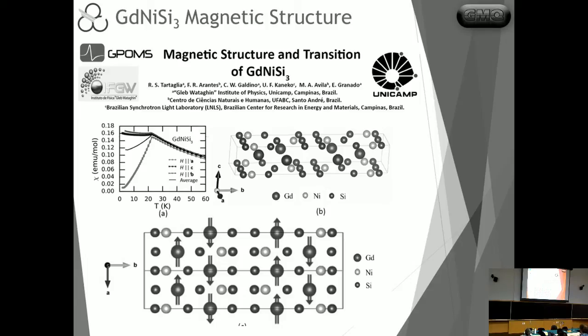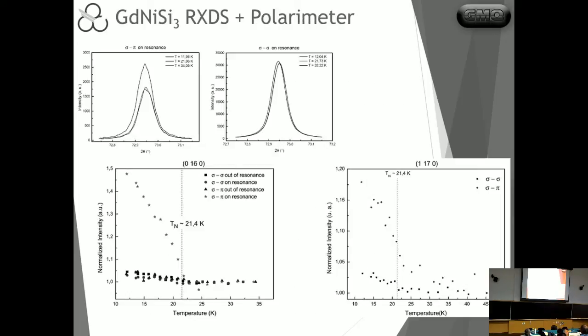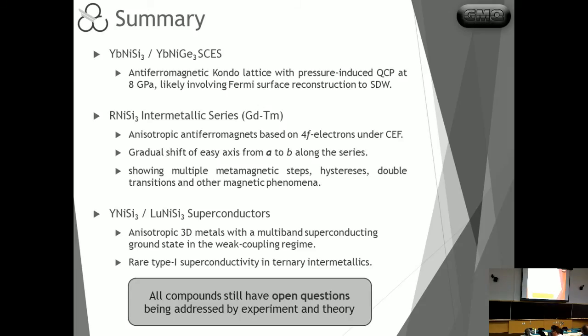And in order to do this, because this system actually has a commensurate magnetic alignment with the lattice, they were very creative in producing a two-step polarization technique which allows us to resolve the magnetic peaks when they are buried within the crystallographic peak. And this is also an interesting development that allows us to really see how the magnetic transition develops in this case. So with that, I just want to finish with the final messages here.